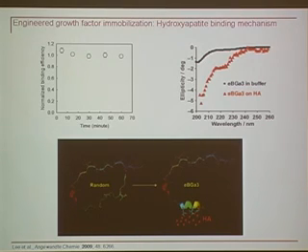If we look at the mechanism for binding, and I won't get into this in too much detail, but just briefly to give you an idea of how this might mimic what happens in osteocalcin binding. One, the binding is very fast. Within 5 minutes, we see 100% of the binding complete, essentially. And we've tried to run the experiment faster than this, and in each case, we see complete binding. So it's really quite a rapid immobilization.